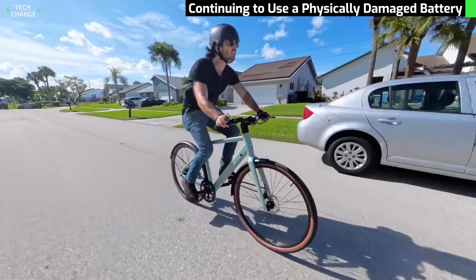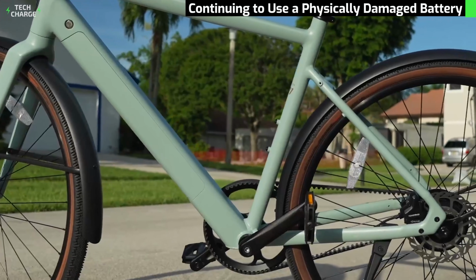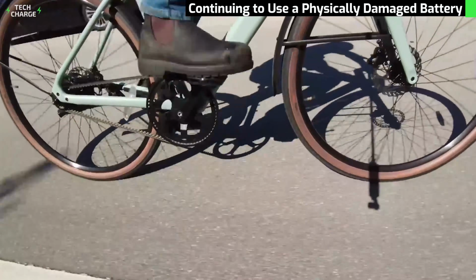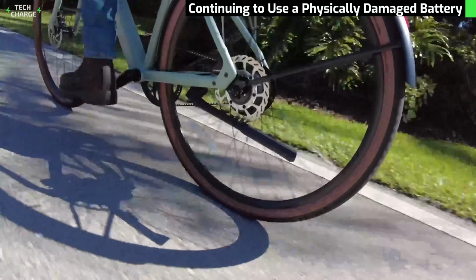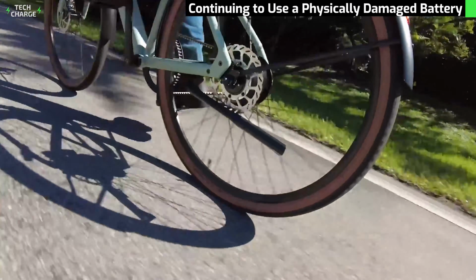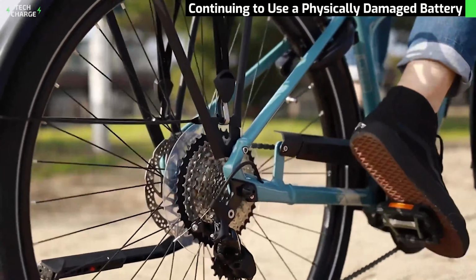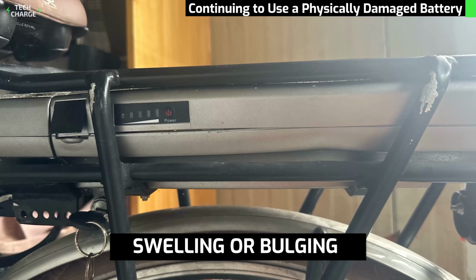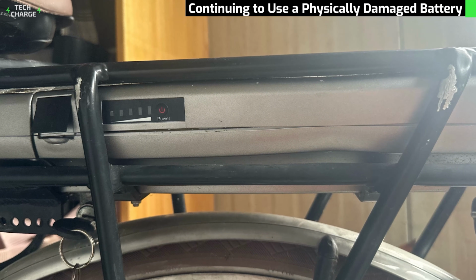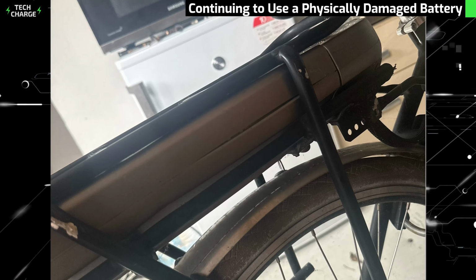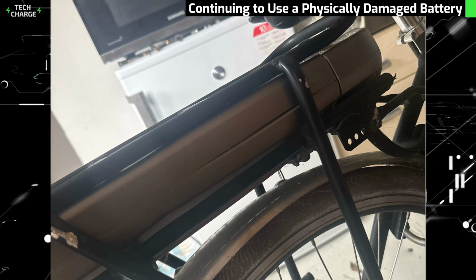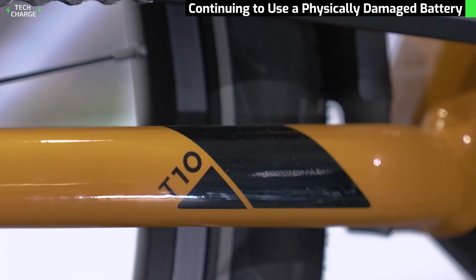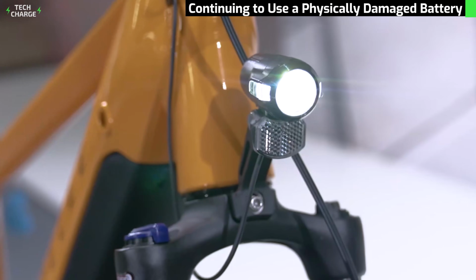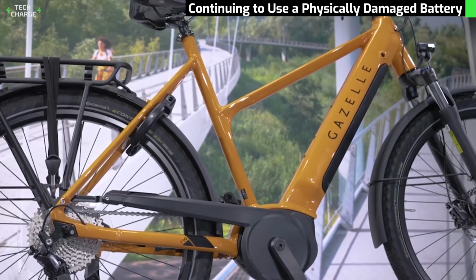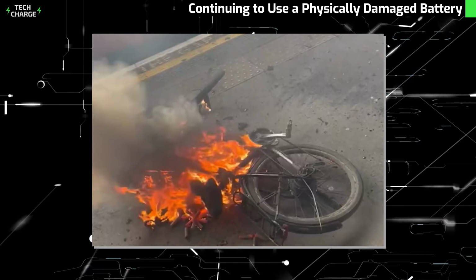External warning signs should trigger immediate removal from service. Dents in the battery case indicate the internal cells absorb significant impact force. Punctures or cracks in the housing mean the protective shell is breached, exposing internal components to environmental contamination. Swelling or bulging of the case is perhaps the most critical warning sign because it indicates pressurized gas buildup inside the sealed container. This pressurization dramatically increases explosion risk because the battery is essentially a pressure vessel that's been compromised.